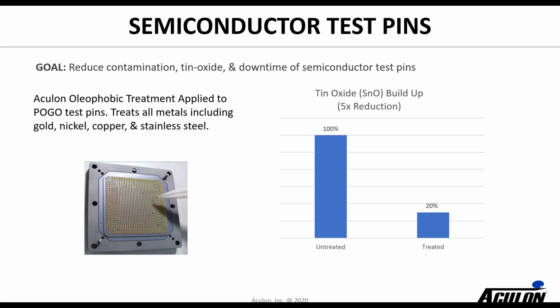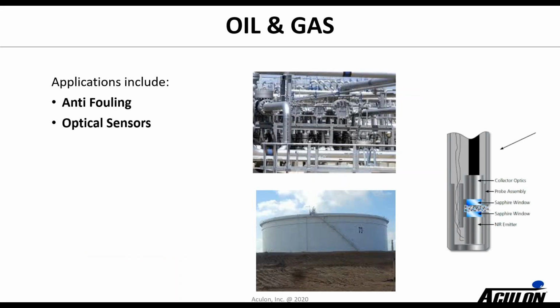In this case, you basically want to increase the longevity of these test pins. The test pins get mucked up by tin oxide buildup. So if you have an untreated versus a treated one, you can see we get a 5 times reduction in the amount of tin oxide buildup, which increases the longevity of the pins and reduces the cleaning of those pins. So it's an interesting example again of an oleophobic type application.